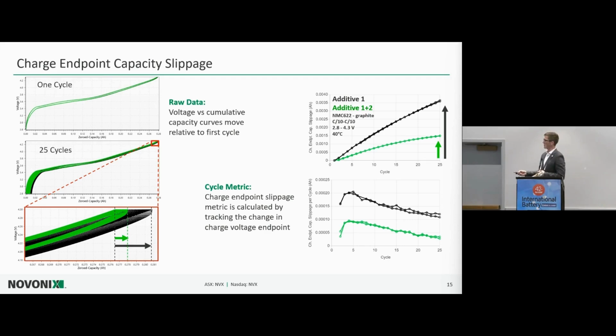And we're going to do this very consistently cycle to cycle. What that means the next time we charge up, if we start back at where we landed, not quite at 0, we actually typically overshoot the last charge endpoint, because we're going to overcount again. And then we're going to discharge and fall a little short, charge up again. And what this means is our voltage curve ends up kind of walking out to the higher capacities here. And the rate at which it does this relative to other cells has to do with these slippage-based mechanisms, this overcounting during charge, undercounting during discharge.